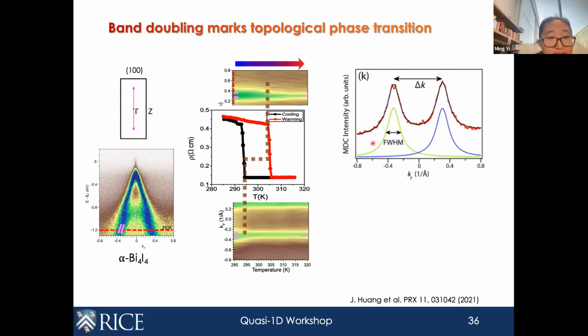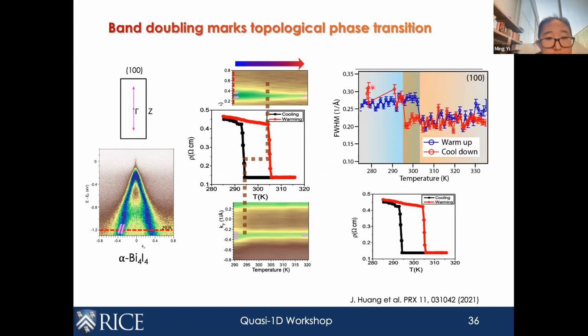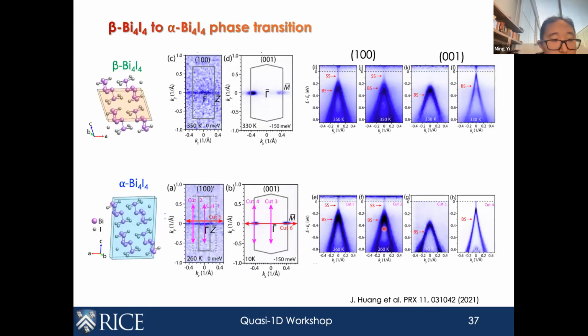So just to quantify this, we can fit the width of these peaks as a function of temperature. And for the warm up and cool down, you can capture that there's a jump in the full width at half max. And that's consistent with the resistivity measurement. So this indicates indeed our sample goes through this band doubling effect. Okay, so having established that, we want to look at what happens to topology here.